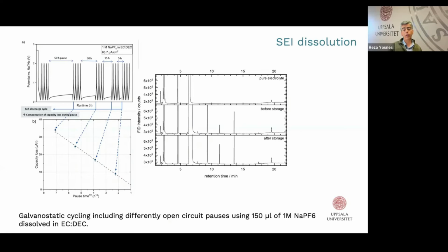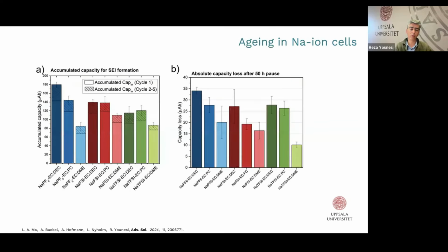Using different analytical tools, including XPS and GCMS and so on, we could see that the electrolyte composition is changed before and after storage or after pause. You see in the middle and bottom that there are some minor peaks. They are very minor and perhaps difficult to observe, but still possible to see minor changes before and after storage, which again indicates that SEI dissolution is occurring during the pause.